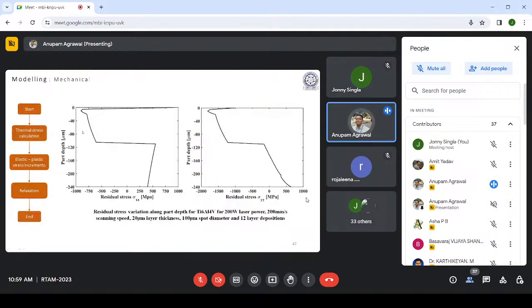Finally, the residual stress variation along the part depth. We have tried to do the simulation for a number of layers. Let's say after 12 layers got deposited, the 0 here shows the surface. Along the part surface, just at the surface, the residual stress is very high, tensile residual stresses. However, as we go down, the nature of residual stresses changes. Sometimes it goes immediately into compressive residual stresses, but there is a very huge tensile residual stress at the top surface, which is unwanted.